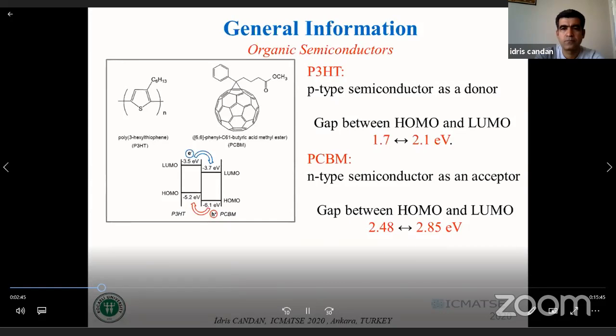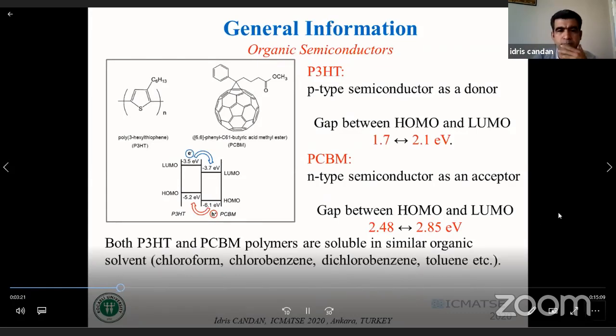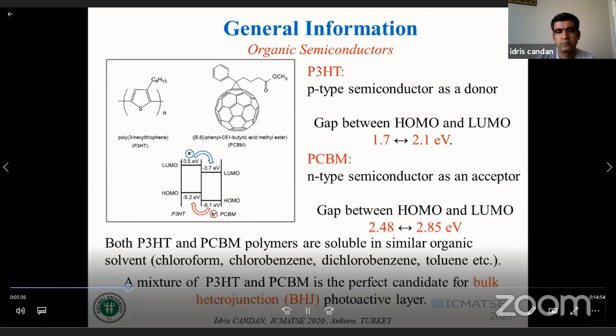In this work, P3HT and PCBM were used. P3HT is a P-type organic semiconductor used as a donor, and it has a gap between HOMO and LUMO levels of between 1.7 and 2.1 electron volts. PCBM is an N-type semiconductor used as an acceptor, and it has a gap between HOMO and LUMO levels of between 2.48 and 2.85 electron volts. Both P3HT and PCBM polymers are soluble in similar organic solvents like chloroform, chlorobenzene, and toluene. A mixture of P3HT and PCBM is a perfect candidate for bulk heterojunction photoactive layers.